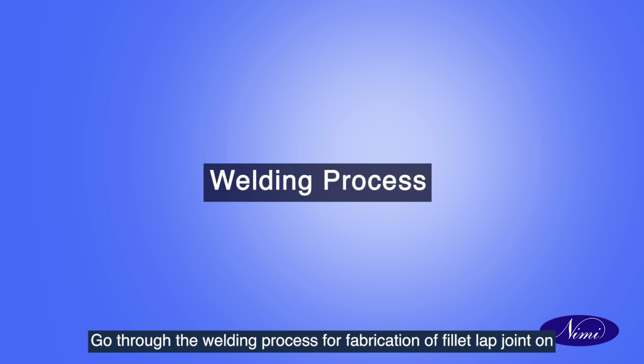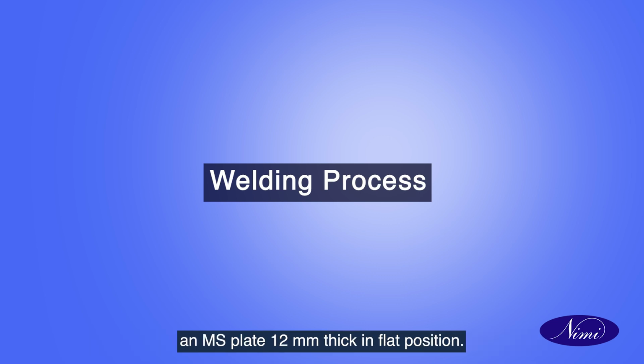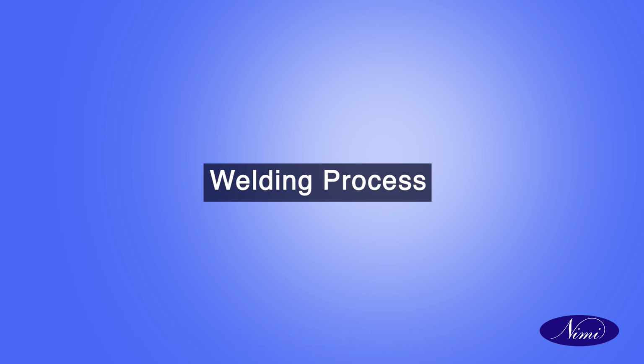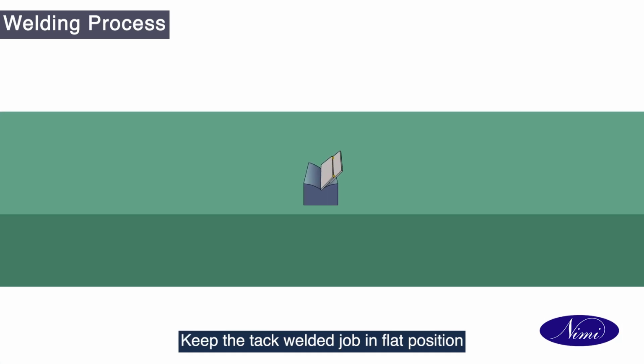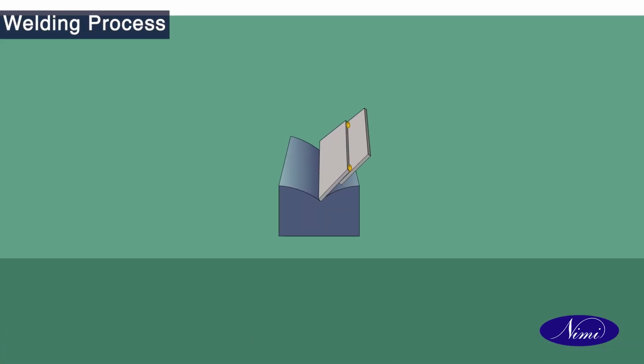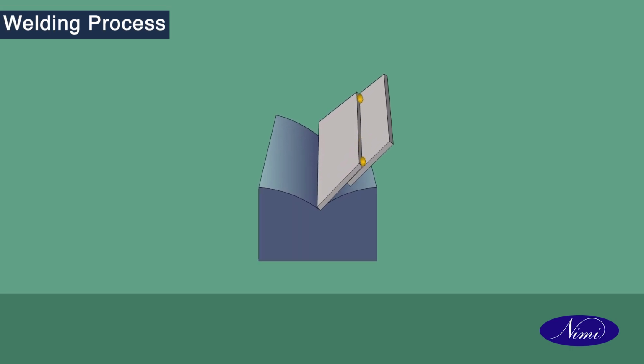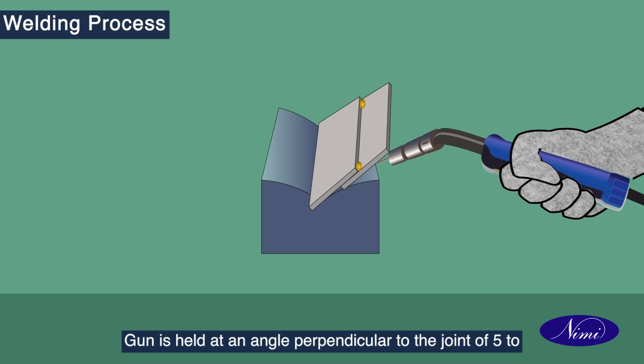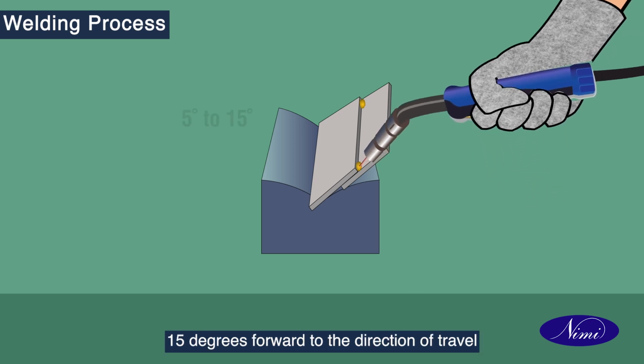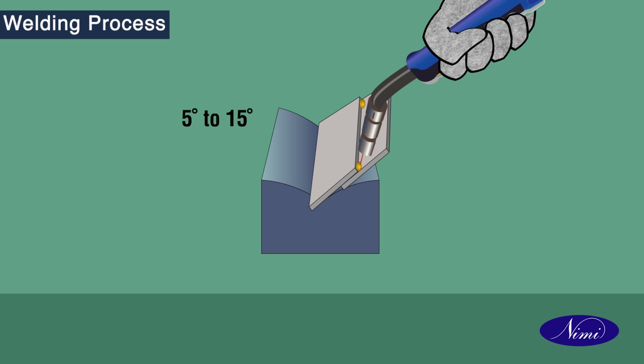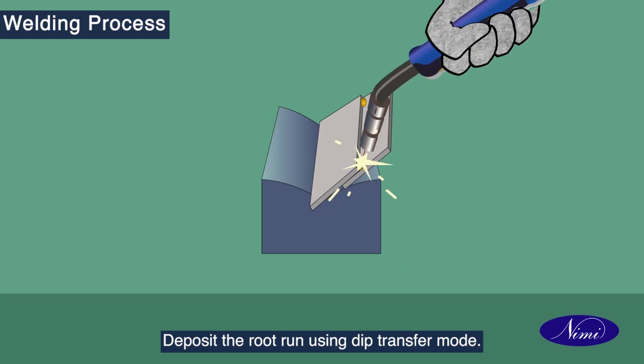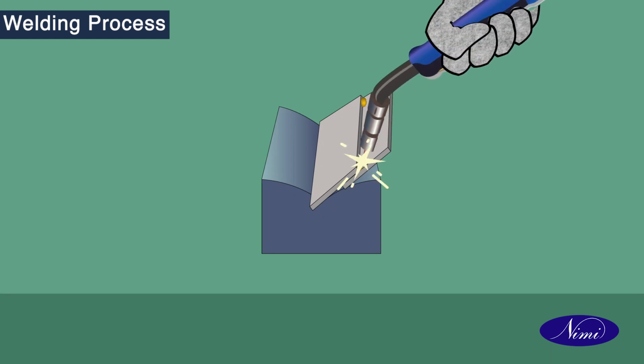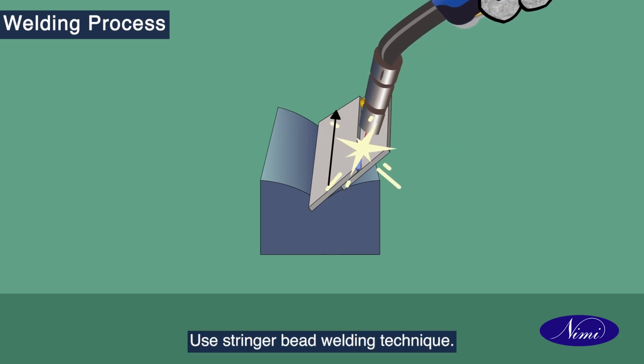Go through the welding process for fabrication of fillet lap joint on an MS plate 12 mm thick in flat position. Keep the tack welded job in flat position on a welding table. The gun is held at an angle perpendicular to the joint of 5 to 15 degrees forward to the direction of travel. Deposit the root run using dip transfer mode. Use stringer bead welding technique.